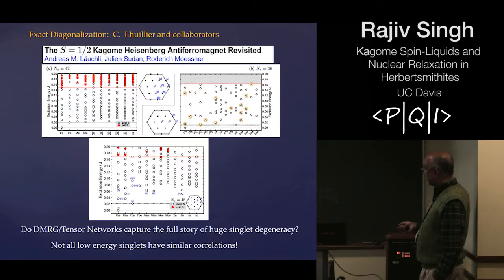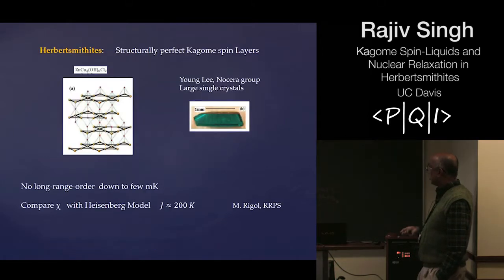These are again the quantum numbers of the system, and this is the excitation energy, but what you see is the red are the triplet states and the open circles are the singlet states. Again you have a huge number of singlets whether you go to 42 or 48, and this is not even a complete diagonalization. These are Lanczos type methods that can pick up most of the low lying states but not all, and you can see that you have a huge number of singlet states still below the lowest triplet state, and DMRG simply has not found this evidence for a very small singlet gap and a much larger triplet gap and this huge singlet state degeneracy. So I think there is still something to be learned about these models.